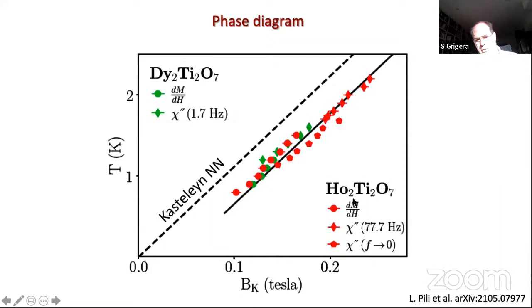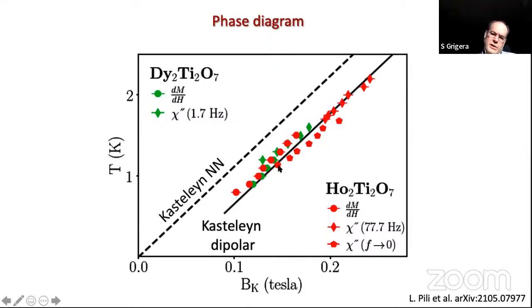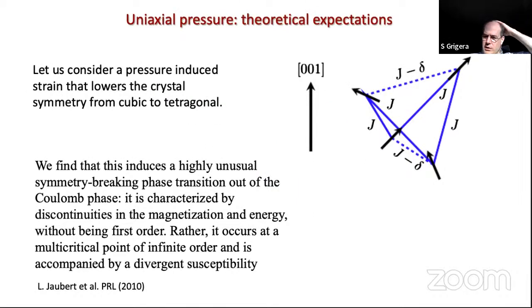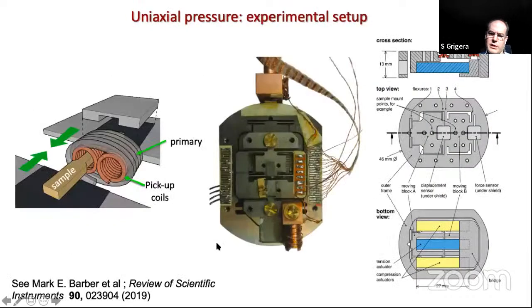And as I said, for the case of holmium, the J was twice what you would expect. So in principle, if this were a normal metamagnetic transition, we expect the critical field to be twice as big in the case of holmium than in the case of dysprosium. Let me use the last 2 minutes by telling you what you would expect to happen once you put uniaxial pressure. Essentially, what you're doing when you're putting uniaxial pressure is you're changing these two interactions compared with the rest. And essentially, you're going from cubic to tetragonal, and you will induce a polarization even at zero field. And if you look in detail at the theory of this, you'll find that this is a very unusual transition, that it's an infinite order transition.